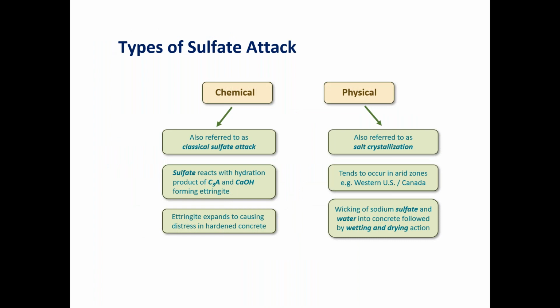All right. So as I said before, sulfate attack is widely classified into two different categories. You have the chemical attack. Some people refer to this as the kind of sulfate attack you learned about in college. It's the traditional sulfate attack, and it has to do with sulfates entering into concrete, whether they're already there or whether they've intruded from external sources, and they interact with the hydration product of C3A and calcium hydroxide, or free lime, and the product that is formed is ettringite. And the problem with ettringite is that it is expansive.